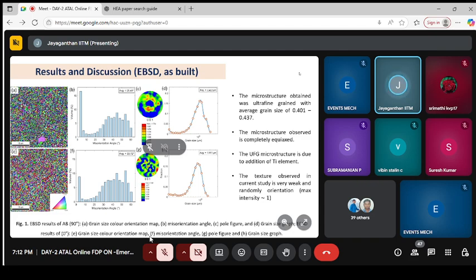If you are able to connect with what I said so far: the 3D printed aluminum 202 alloy, with titanium added. If I see through the EBSD camera, the internal microstructure is made up of several grains of crystal. You have several colors. What does it indicate? What is the size? You can see that you have well refined, ultra fine grained microstructures. The size varies from 0.401 to 0.437 micron.